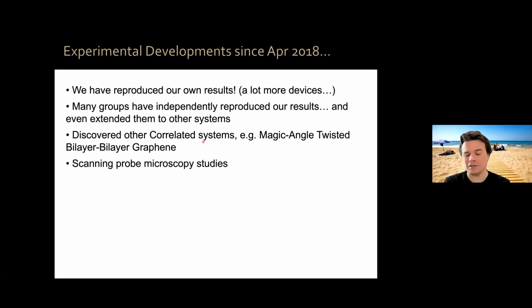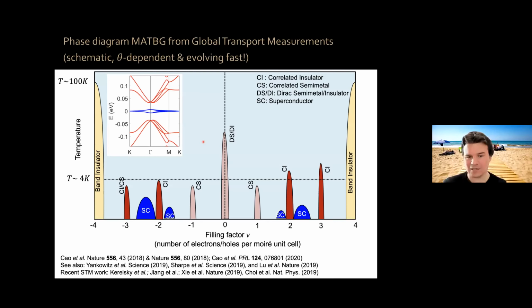The community has also been doing scanning probe microscopy studies, scanning tunneling microscopy, scanning nanoSQUID, plenty of such studies. Let me tell you about one in particular, which I think has given us a lot of insight. The phase diagram of magic angle twisted bilayer graphene was initially mostly determined by global electronic transport measurements. That was our study at Columbia and Santa Barbara, and the study at ICFO. What we saw, and this is schematic, it's twist angle dependent and evolving fast, but to zeroth order, is a plot of temperature versus filling factor nu. What is this filling factor? It tells us how many electrons or how many holes we are putting per moiré unit cell, electrically.